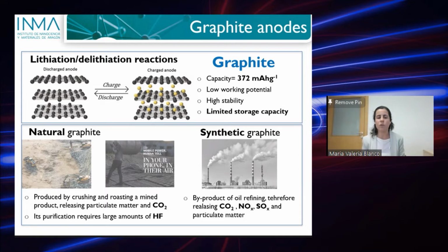So on one hand, we have this problem of the limited storage capacity. But on the other hand, we have the problem of the source of graphite. Commercial graphite can be produced either from natural graphite or synthetic graphite. Natural graphite is obtained by crushing and then roasting a mined product. But to get the purification grade that we need for battery grade anodes in lithium-ion batteries, this natural graphite has to undergo a lot of purification steps, which needs a large amount of HF and also sodium hydroxide, which are harmful to humans and also to the environment.